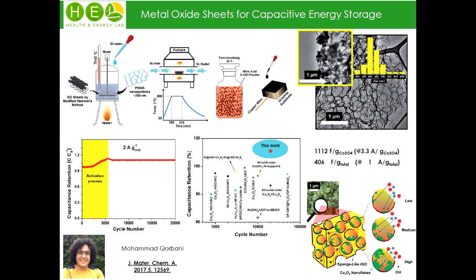We tried to control the performance of the overall electrode by changing the electrodeposition conditions. We found that with a low amount of loading, we don't have any pseudo-capacitive active material, while with a high amount of loading of flakes, we may block the porosities of the sponge-like graphene, and because of low conductivity inside the flakes, the overall capacitance is reduced. But we found the optimum condition for growing such flakes inside the sponge-like graphene.